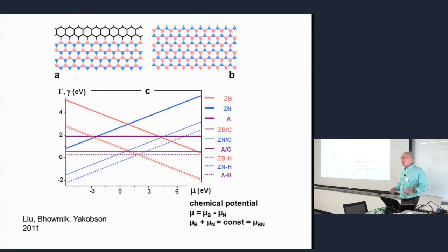And then you realize, oh, now actually there is no given energy of the edge because of this extra degree of freedom in the Gibbs equation, right? F equals C minus P plus 2. You have a chemical potential, which is undefined by the material itself. You only have a defined potential for BN together, right? So the only well-defined quantity is this: mu B plus mu N is constant, because this is the energy of formation of BN. But individually, they can be different depending on gas phase or depending on some additional conditions which are not really in the picture. So the result is that all these energies of edges or interfaces in these hybrid structures are now functions. They are not fixed numbers.